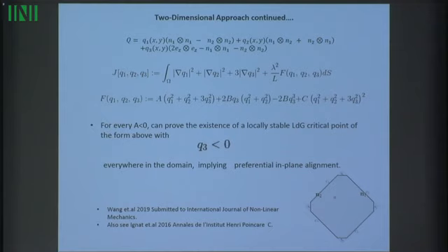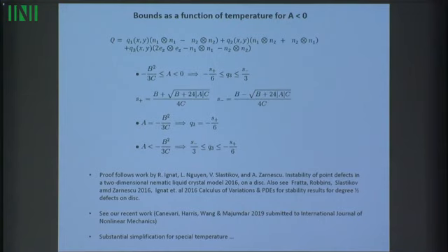Well, Q3 is the eigenvalue associated with Ez, which is one of the fixed eigenvectors, and this result is physically telling you that there is a physically relevant critical point with negative eigenvalue associated with Ez, which means that the molecules are really in the plane of your square. So there is a physical interpretation of this result, that you have these physically relevant critical points which have this in-plane behavior.